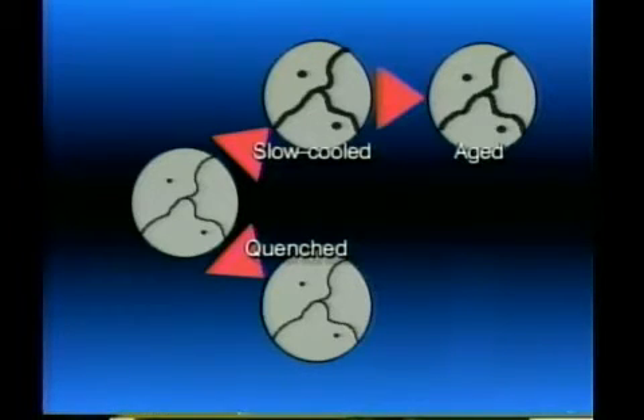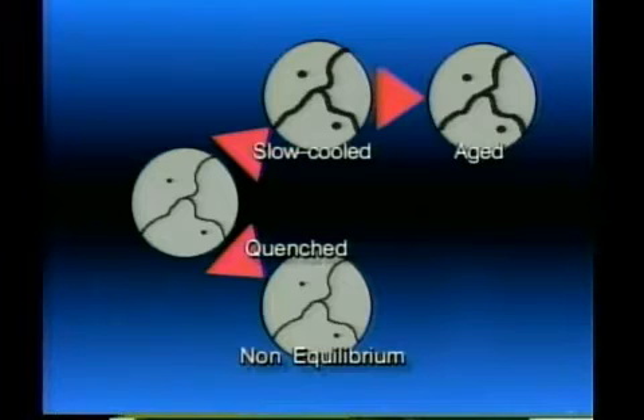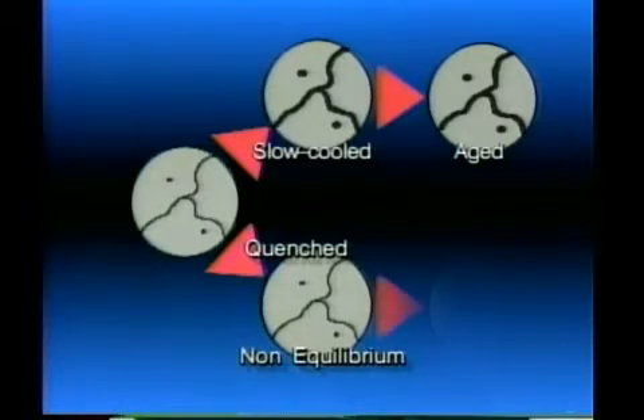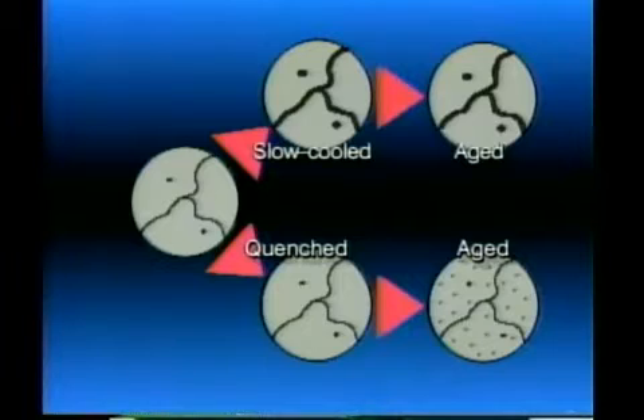In this frozen state, the alloying elements are under a severe stress and do not like being trapped in their current location. In technical terms, this condition is called a non-equilibrium condition. These alloying elements, by themselves, even at room temperature, will start to move or diffuse to achieve an equilibrium condition. The movement of these atoms after the quench is called aging. During aging, the hardening elements move short distances and come out of solution or precipitate in local areas, resulting in significant strength increase in the part.